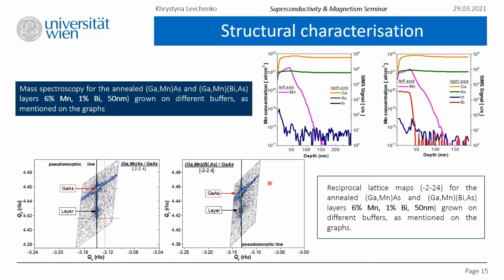One would expect a cubic crystal structure for gallium manganese arsenide because gallium arsenide exhibits it. A cubic crystal structure, just to remind, has the highest symmetry. But due to the epitaxial growth of the bigger lattice unit of gallium manganese arsenide upon the smaller one, gallium arsenide, the layer symmetry lowers. So that is why I'm saying that we are compressing the top layer to fit the bottom one. In fact, this results in tetragonal deformation of the lattice unit. The images seen here in the left down corner are the results of the reciprocal lattice maps measured along the -2, -2, 4 crystallographic directions.